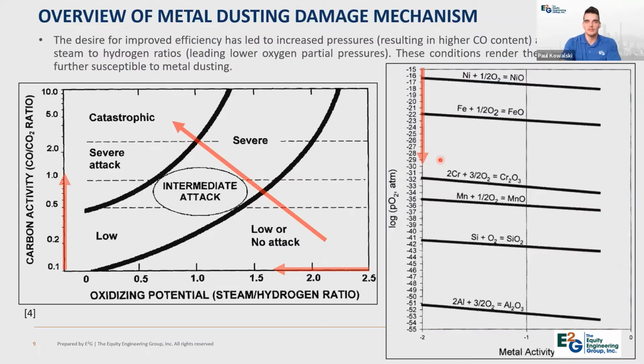So recently, in regards to operating trends, the desire for greater efficiency has led to some changes or different directions or goals on the front end of the ammonia production plant, specifically in the syngas loop. And so increased front end pressures, which is resulting in higher carbon monoxide content and therefore increasing the carbon activity, as well as lowering the steam to hydrogen ratios, which consequently reduces the oxygen partial pressure.